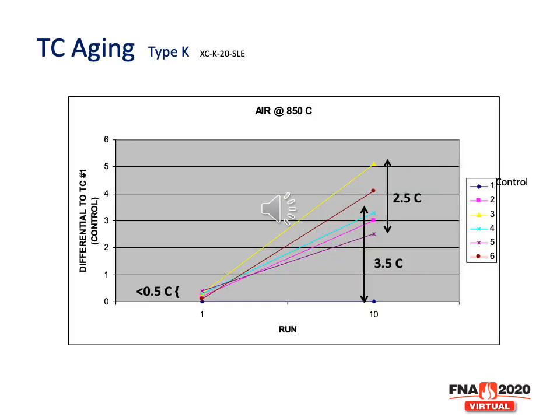Another issue you can run into is thermocouple aging. And this is with type K thermocouples. We were running a project where we were attempting to get plus or minus 1 degree C across the 25-inch wide belt through the peak temperature. We were having some issues, so we finally took brand new thermocouples, 6 of them, and ran them down to see the difference, all right next to each other, very close to each other. We found that they were within about 0.5 degrees C of each other on run number 1.